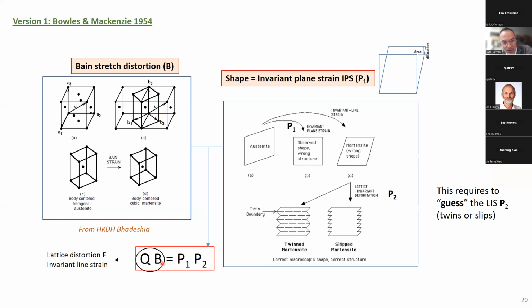So you make your theory with, on one side, the Bain stretch, and on the other side, the invariant plane strain. To make it coherent, you multiply on the left by a rotation matrix, and you combine on the right with a simple shear. Why do you do that? Because you can prove that this rotation combined with Bain is an invariant line strain. It leaves a direction invariant.